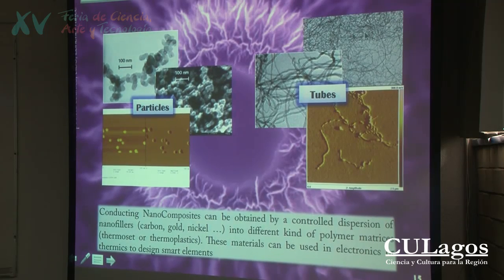And you can have also nanofibers, nanotubes, which have a very high aspect ratio. Typically, the nanotube's diameter is 10 nanometers, and they can be as long as several microns, in some cases several millimeters. So you can imagine very long filaments that are completely entangled. And the interest of this nanofiller is that they can make polymers, which are initially insulating most of the time, electrically conductive with only a small amount. So these nanoparticles can be used as a dopant of insulating materials.